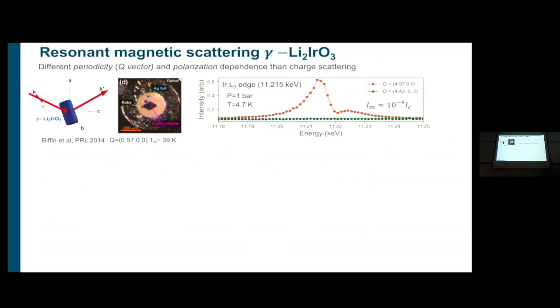So here is just to show you that if you put your sample in a pressure cell and you scan your energy through the resonance, the iridium L3 resonance, you see this large enhancement, and the wave vector is 0.57. That's exactly the position of the magnetic order, of the spiral order. And if you move a little bit away from this wave vector, there is no magnetic scattering intensity. And if you go off resonance, the intensity becomes very small. So we can measure this. You see the signal to noise level is very nice. This is 10,000 times weaker than the Bragg peak nearby, the 400 lattice or charge peak.